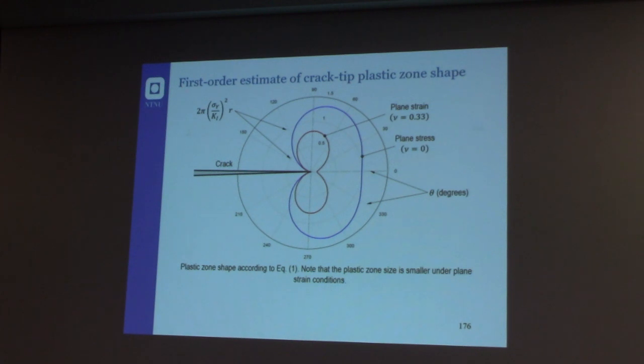So if you consider an estimation of the plastic radius, it's always very convenient to be able to estimate in some way the plastic radius of your material. If you have a crack, you always have the possibility to understand the size close to the crack inside which the material is over the yield strength, so you can measure the radius and define it as the plastic radius of the material. If the plastic radius is very small, you can apply linear elastic fracture mechanics without any problem. If the size increases, probably you need to go through a more complex model considering elastic-plastic mechanics solutions.